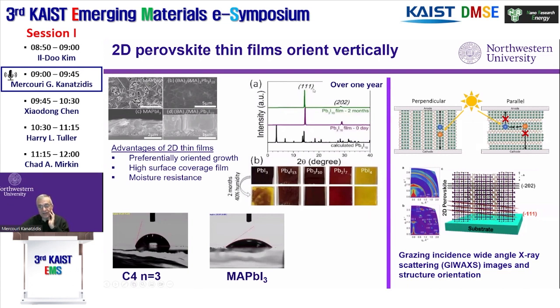But this was a pleasant surprise, the very strong orientation, because if you want to make a device like a solar cell that requires electrons and holes to move up and down, perpendicular to the device, you want this orientation. You don't want this horizontal orientation where it's a blocking direction, because of the organics. And we studied this by grazing incidence wide-angle X-rays. And these things, in fact, diffract like single crystals, although they're not single crystals. So they have these discrete spots rather than the rings here. So that was really a pleasant surprise because that allows you to make a functioning device. And that's what we were worried about with the 2Ds in the first place.